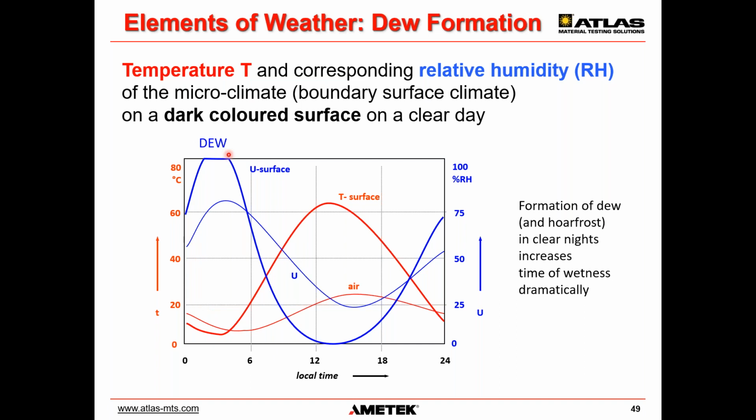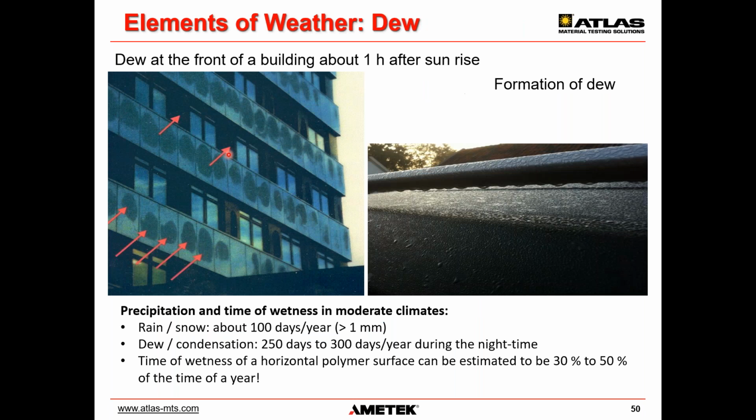So time of wetness on the one side by rain, but even more critical is the time of wetness by dew. And that's the case in tropical, subtropical environments, Florida, Chennai, but also Europe, Northern America. Many areas have dew formation almost every day. So a critical factor of weathering is done by dew. And that's very important.